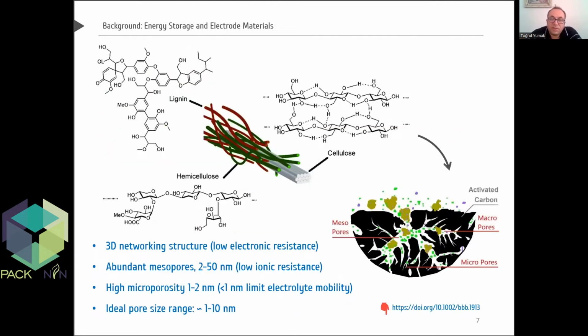Among the carbon-based materials, biomass-based activated carbons with 3D networking structure, abundant mesopores, and high microporosity are good candidates for the electrode active material. The 3D networking structure provides low electronic resistance, while the abundant mesopores provide low ionic resistance and a high transport rate of electrolyte ions.